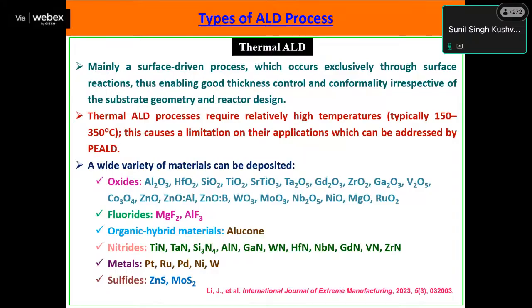Again, there are a lot of different ALD processes. One is the thermal ALD process. Here you use normal heating, up to 150 to 350 degrees Celsius, and a variety of materials can be deposited. Like I mentioned, mostly this is used for oxide materials. Of course, people started with some nitrides and metals, but this is not much required. Why would we waste ALD to grow metals? It is better to grow metals using an evaporator or sputtering system. That is the reason it is mostly useful for oxides.